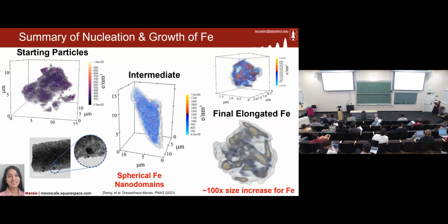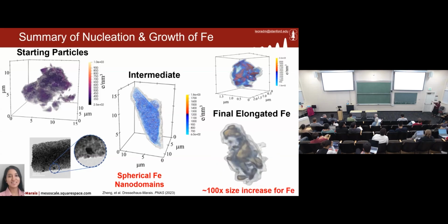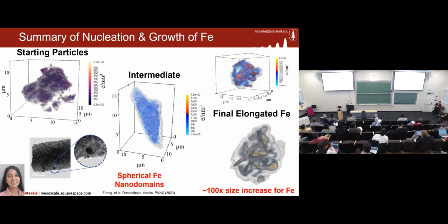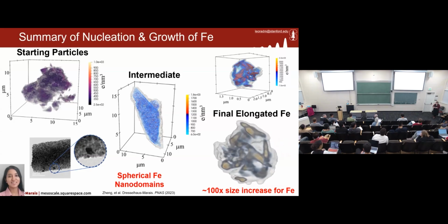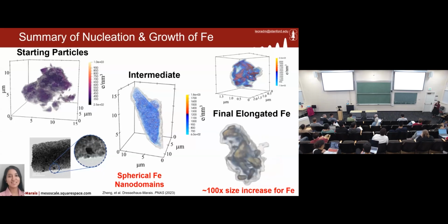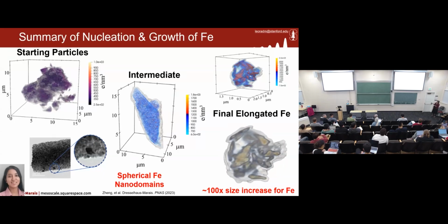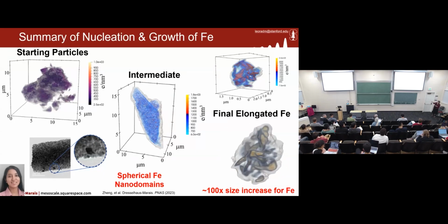And then finally, we end up seeing at the very end this 3D structure where actually the length scale here is much larger. So we see now a 100-fold increase in the size scale that corresponds to the iron alone in this material, and that corresponds now to just the metallic phase.